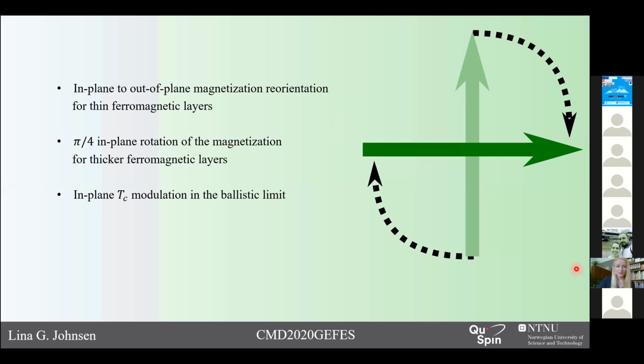So just to sum up our results, we have predicted an in-plane to out-of-plane magnetization reorientation for thin ferromagnetic layers. This has not yet been shown experimentally. We have also predicted a pi/4 in-plane rotation of the magnetization for layers of the ferromagnet that are thick enough to enforce in-plane magnetization, and this has been supported by experimental results. And we have found an additional in-plane critical temperature modulation in the ballistic limit, compared to what has been found experimentally in the diffusive limit before. Thank you very much for your attention, and you're free to ask questions.